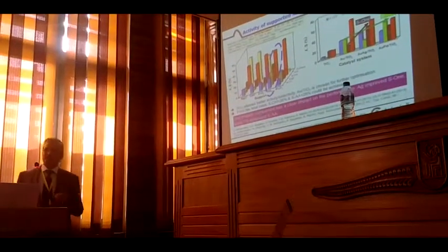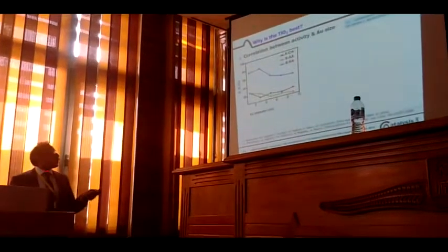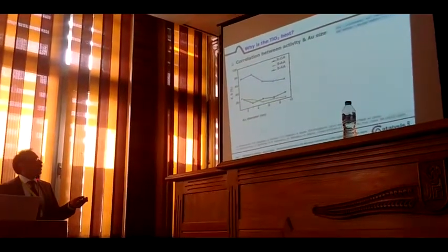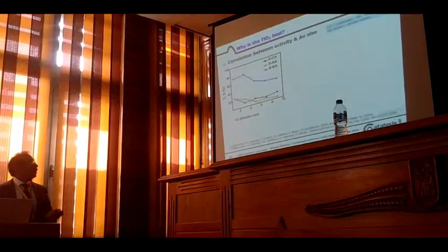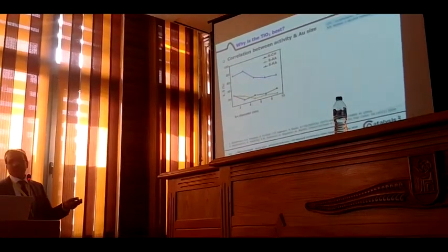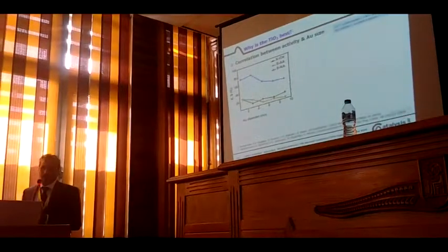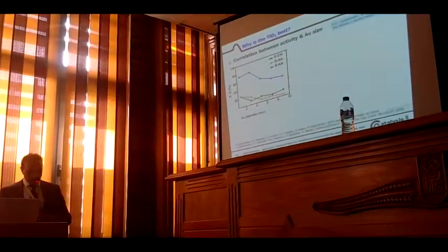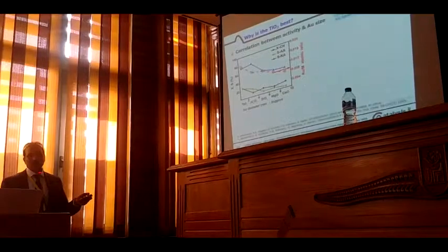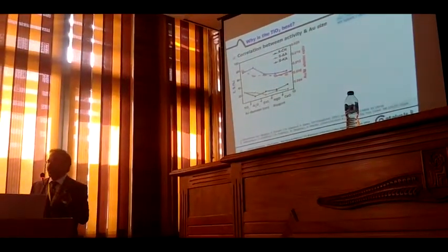Then we were also curious to know why TiO2 is the best compared to other supports. Is it only the particle size or is something else also responsible for this? To check that, I made a diagram here, particle size versus X, the conversion, and S, the selectivity of KA and the selectivity of adipic acid. So you can see that the smaller the particle, the better the performance. In addition to particle size, we also used XPS to estimate the surface composition and compared all 5 supports. You can see that the gold to metal ratio is high in the case of titanium compared to other supports. That means there is an enrichment of gold on the surface.